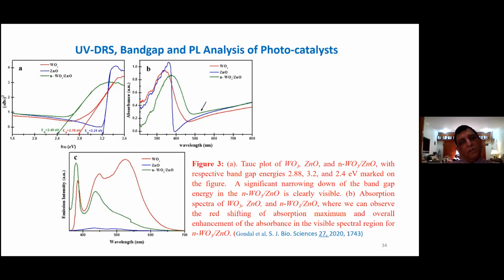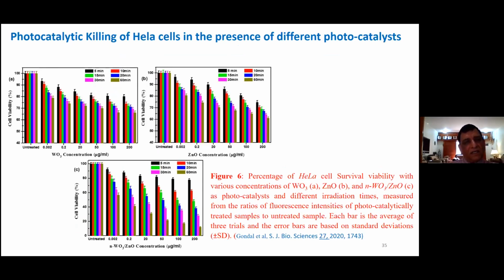That means pure WO3 is not good for our work, because whenever we bring electrons up, maybe 50% or more jump back to the valence band and light is emitted. But when we put in WO3 ZnO, you can see the emission has decreased a lot. We are controlling that basically by doping ZnO into WO3 to prepare this nanocomposite. Then we are also controlling the electron-hole recombination process, and in this way the efficiency of our catalyst will definitely be enhanced. And this is the final result.